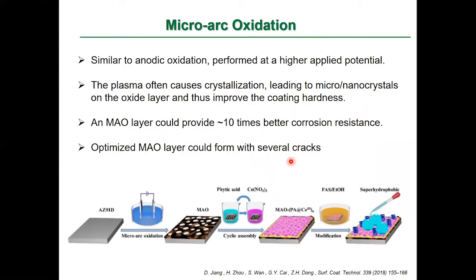So the micro-arc oxidation is similar to anodic oxidation, but performed at a higher applied potential. It can make a thicker oxide layer. It is important for metals like magnesium. Magnesium forms a thicker oxide layer, but it has a porous structure, and so they use conversion coatings to cover that, then subsequently made it superhydrophobic with silicone.